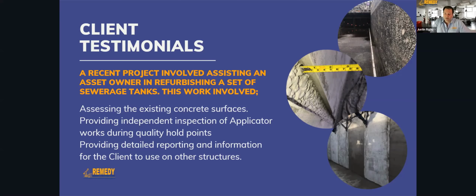So you can see the image in the middle is where they've applied panels of mortar to about 25 mil deep. And there's a gap there where they've pulled the batten out, and you can see what the wall looked like before they started. And the image at the bottom is where, once they've completed all the panels, they've stitched them all up, and they've closed up that gap where the battens are. There is an image in a later slide that shows the finished wall surface after waterproofing, but I'll just focus on this example for a moment.